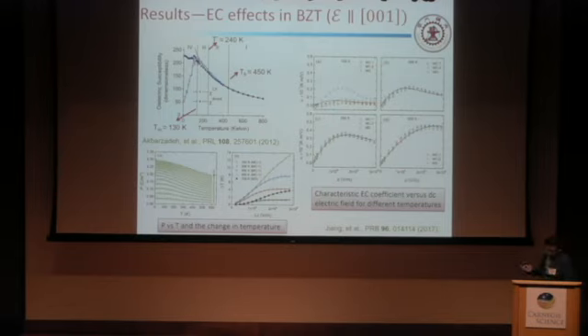So, from the picture, we can see that above Tm, the three methods give nearly identical results, but below Tm, the indirect and direct methods can't give the same results. Because below Tm, the system is non-ergodic. We can't use the normal Maxwell thermodynamic method to calculate the EC effect. So here we don't trust the indirect method, we just trust the direct method.